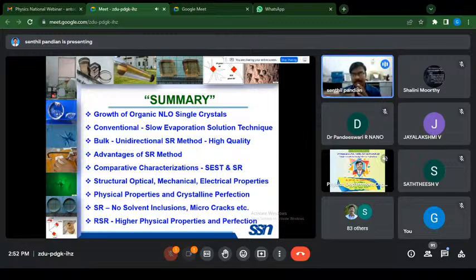In order to avoid this issue, we have slightly modified the SR method. It is called the RSR method, the rotational Sankaranarayanan-Ramasamy method. There we are able to minimize the impurity segregation in the RSR method grown crystal. Under identical conditions, we have compared the physical properties and the crystalline perfection of the SR, conventional, and RSR method grown crystals. The RSR method grown crystals have higher physical properties and higher crystalline perfection compared to the conventional SR and the conventional slow evaporation crystals. So we can use these ferroelectric crystals and nonlinear optical crystals for practical device applications.